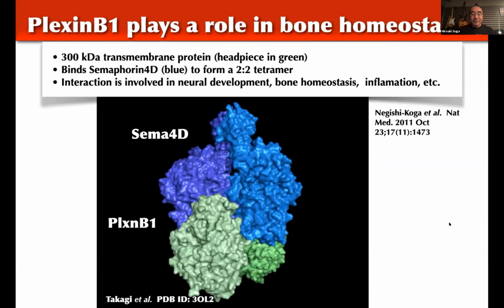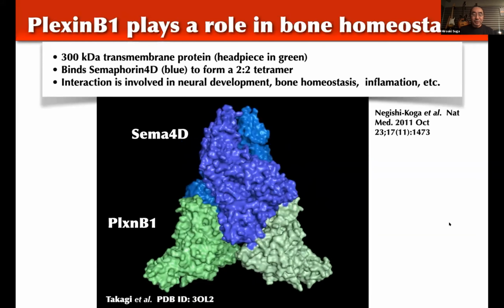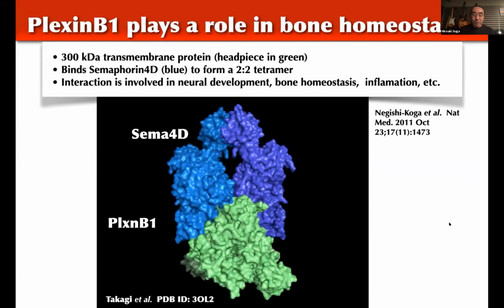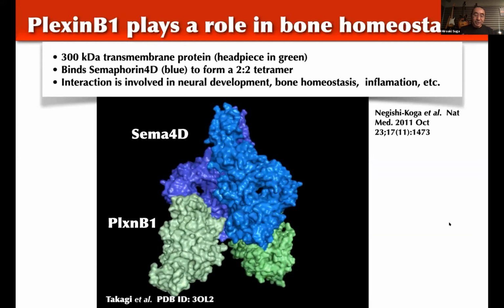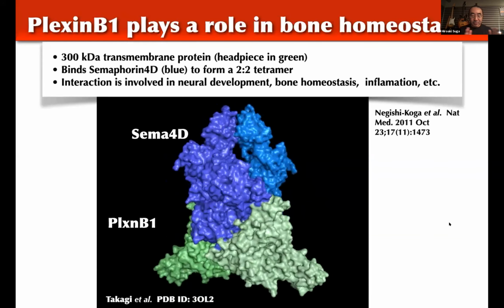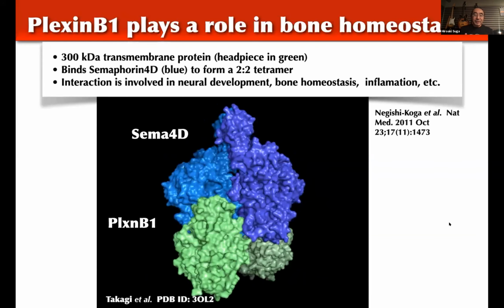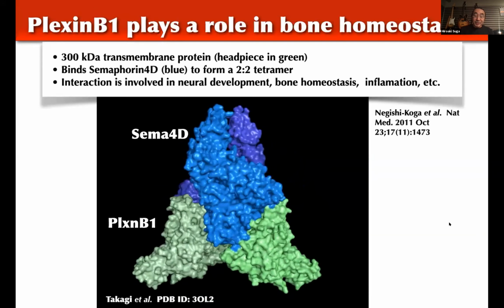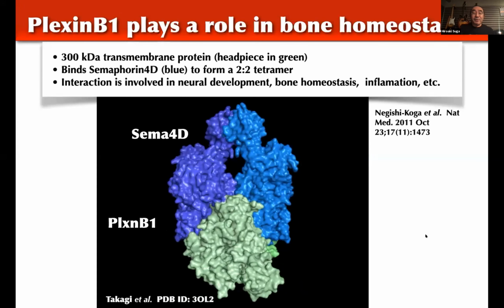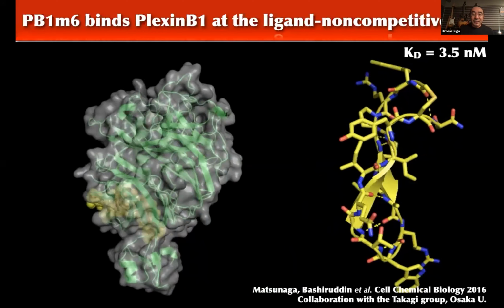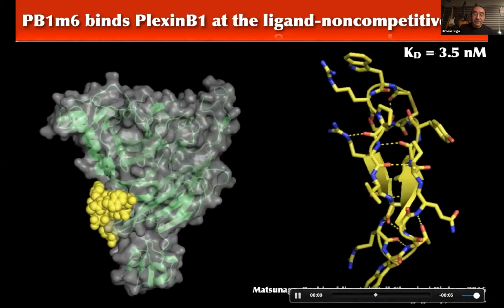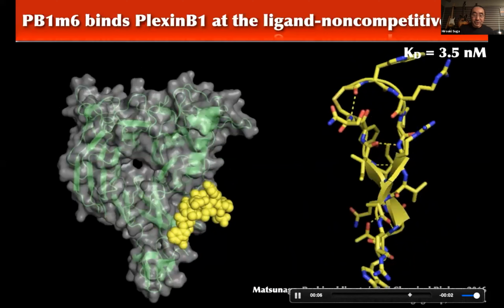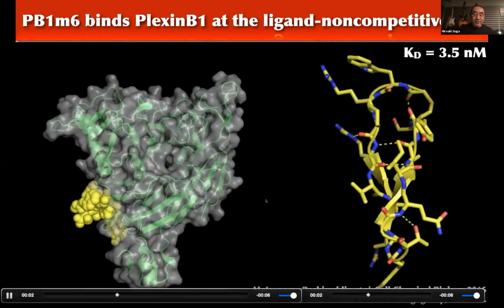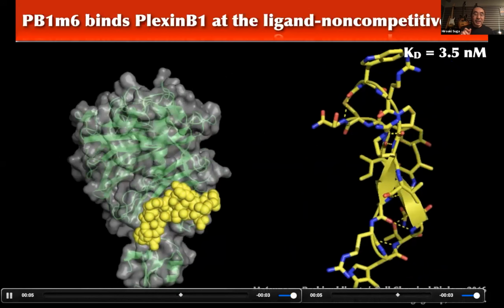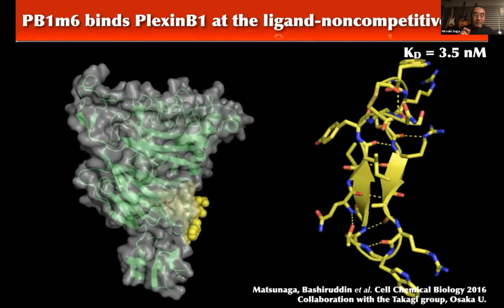bone homeostasis. Particularly in this case, the Semaphorin4D protein interacts with plexin B1 and stops the differentiation of the bones, so you cannot make new bones. So we tried to find inhibitors of this protein interaction. Then we used our technology and isolated a binder with a KD of about 3.5 nanomolar. It's a very strong binder for plexin B1, and this molecule turned out to allosterically inhibit the interaction between plexin B1 and Semaphorin4D.